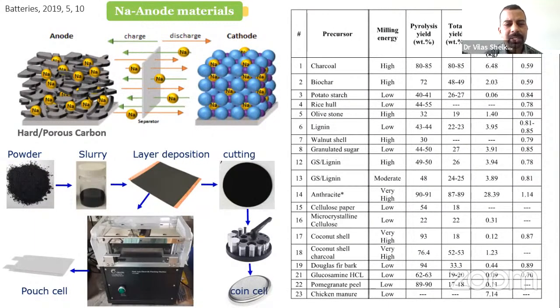After depositing these layers of cathode and anode material, you have to dry it or allow the layer to settle, and then you can cut it in the form of electrodes. For a coin cell, you cut it to the particular size of the coin cell case, and then you crimp it in the form of a coin cell. There you crimp the layers of cathode and anode, and in between you put the separator and the electrolyte. Similarly, to make a pouch cell, you get the pouch case, and inside the case you put single or multiple layers of cathode material and anode material, with a separator in between. Then you put the electrolyte.